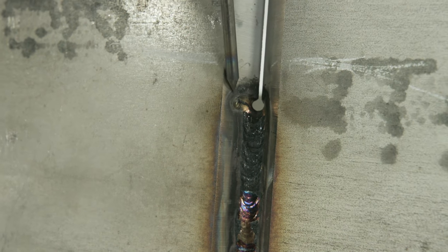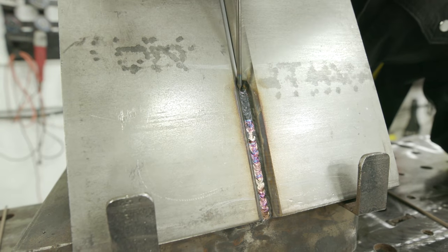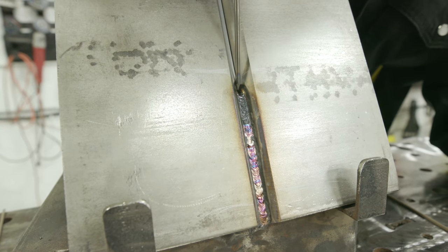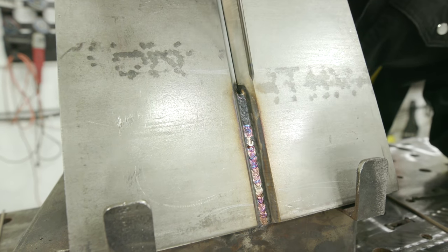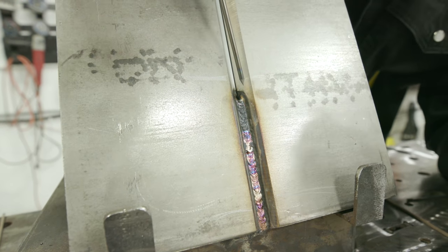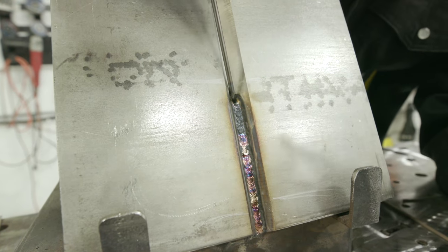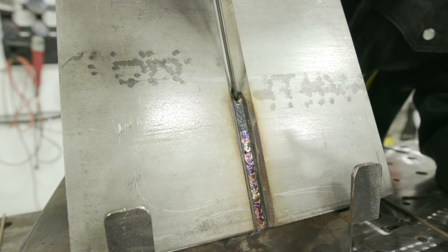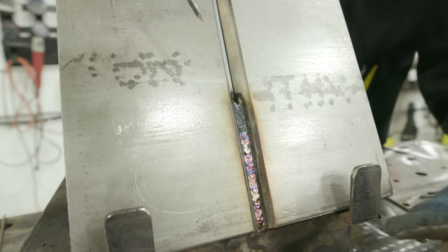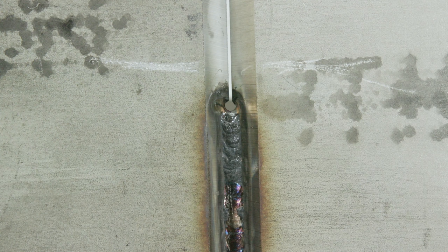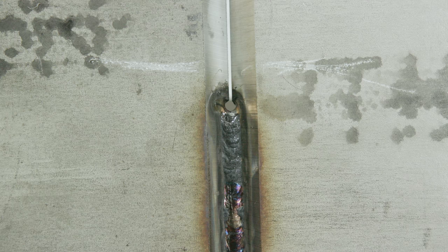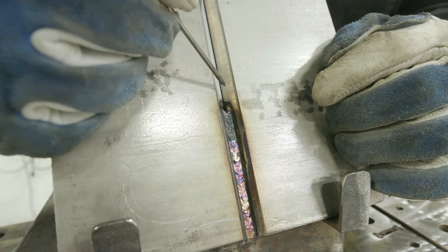See how this got color? That's still good, really a little hot but there's no sugaring. You see this keyhole? That tells me I'm breaking down the wall good, getting penetration. It looks like I'm almost halfway on both sides of plate. The keyhole's a little bit on this side, telling me I'm favoring my left side, so when I restart I want to focus more on both plates.